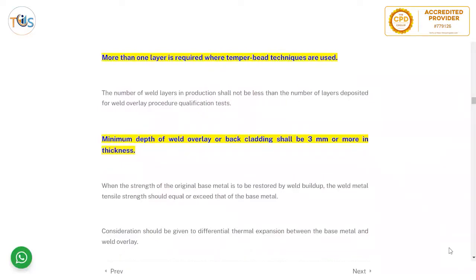Number of weld layers in production shall not be less than the number of layers deposited for weld overlay procedure qualification test. So number of weld overlay layers is an essential parameter. This could be a question. Minimum depth of weld overlay or back cladding shall be 3 millimeter or more in thickness. So minimum weld overlay is 3 millimeter. Potential exam question again: when the strength of the original base metal is to be restored by weld build-up, the weld metal tensile strength should be equal to or exceed that of the base metal. So this is common sense.